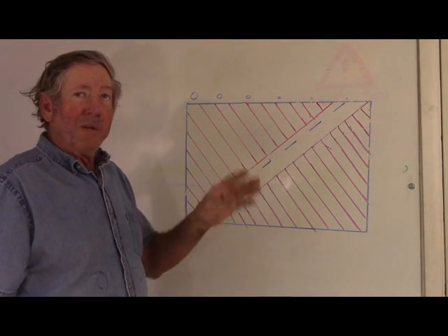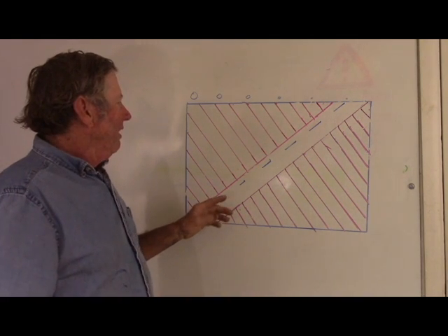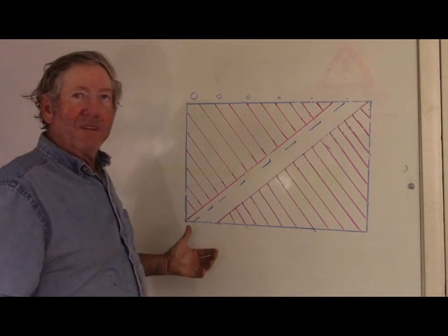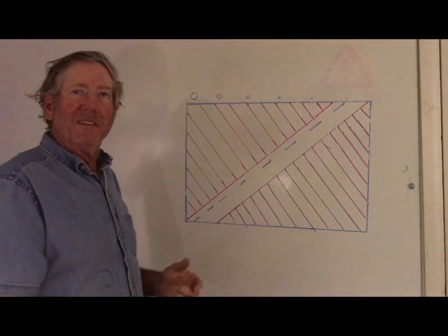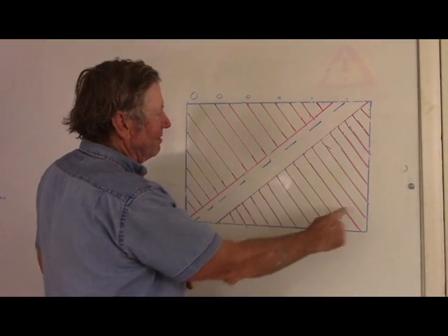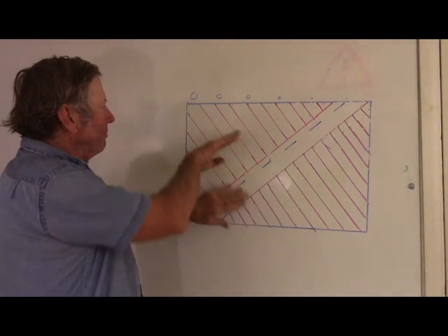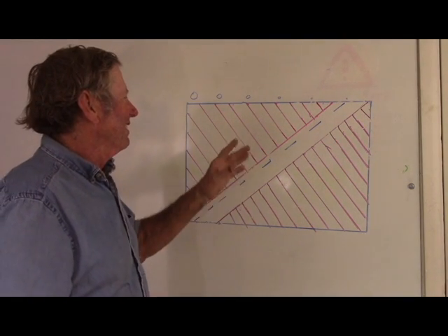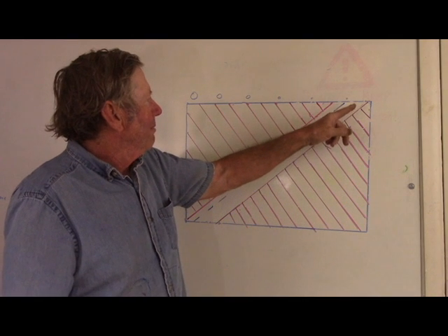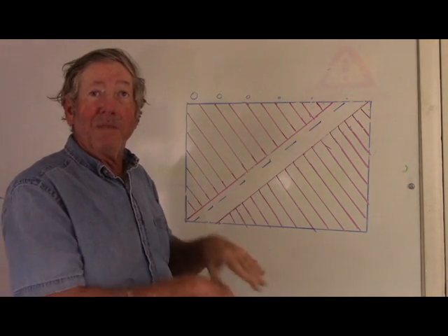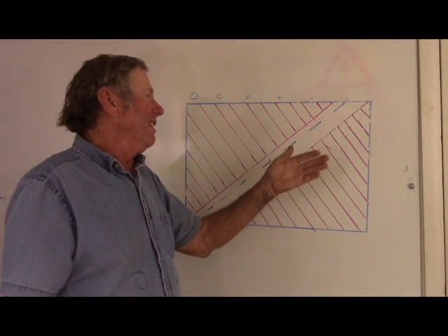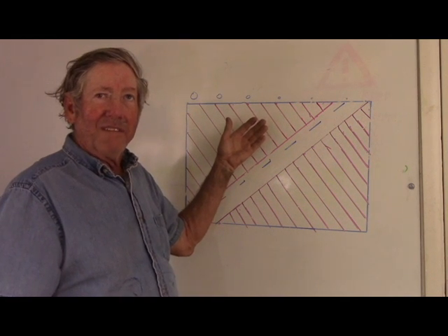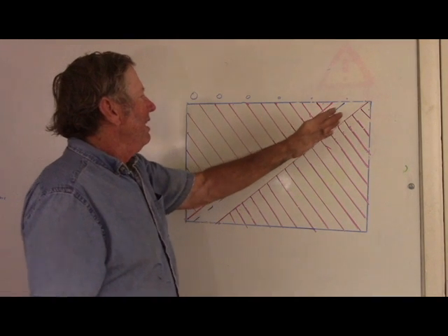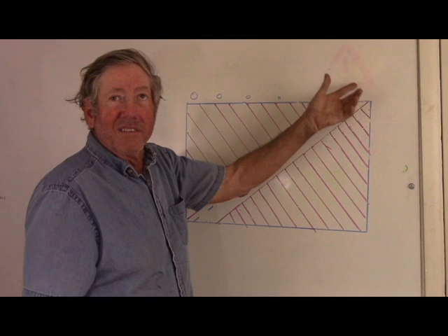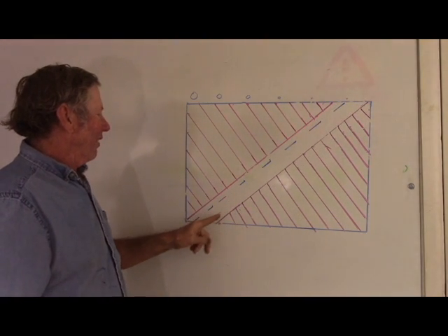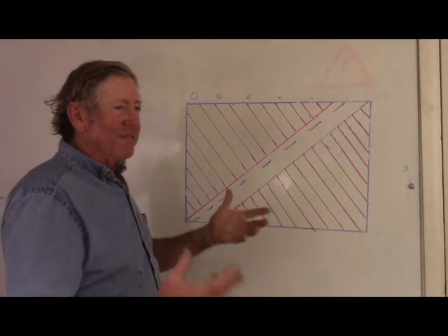When you're leaching, especially with cyanide or one of the slower leaches, then the coarser particles are going to get almost no recovery whatsoever. You're just not going to get into them very much. So this kind of represents the leaching ability. Now there's probably some overlap here, but that would mess up something else I'm going to show you. So, you can't get over 100%. But here, the smaller particles, and this assumes that you have mineral liberation, where every particle can theoretically be either leached or recovered by gravity. Okay? Both will work. Now, in the leaching scenario, the smaller particles, you get essentially 100% recovery, and then as they get bigger, they get harder and harder to dissolve. This would also be if you didn't have complete liberation or something.